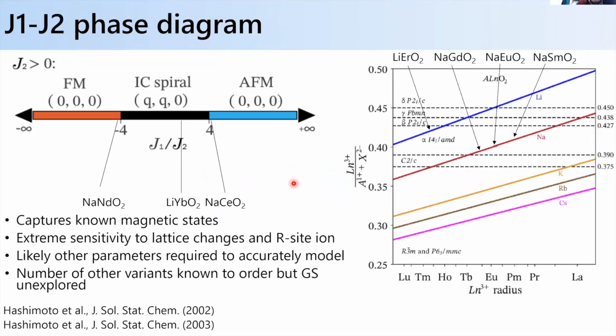Okay. But so then if we look at this proposed phase diagram, right, it starts to look a little weird, right? So we're here at the lithium ytterbium O2, okay? But then for an antiferromagnetic state with Q = 0 order, that means the sodium cerium O2 should be out here, where J1 over J2 is now 4. Basically the ratio has jumped to almost a factor of 2. So, while this phase diagram does capture the known magnetic states, there's sort of an extreme sensitivity to changes in the lattice and the R side ion, right, that we don't fully understand yet. And it could be that other parameters are required to accurately model the system.